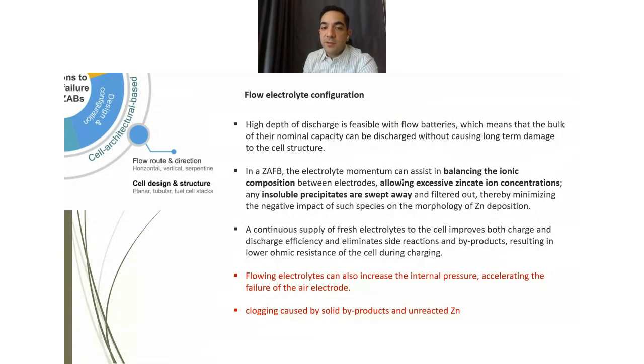And also some insoluble precipitates can be swept away and carried away with the electrolyte and discharged from the system. So a continuous supply of fresh electrolyte to the cell improves both charge and discharge efficiency and eliminates side reactions and byproducts. Also lowers the ohmic resistance of the cell.